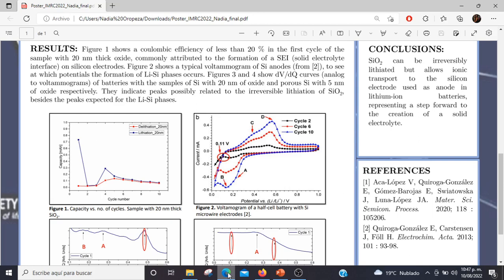As an example, figure 3 shows curves of the first and third cycle of the lithiation period of the silicon electrode for the sample with 20 nanometers of oxide. In cycle 1, there are peaks that disappear in cycle 3. One can be attributed to the SEI formation and the other to the irreversible lithiation of silicon oxide. These peaks are also shown in the 5 nanometer sample. Despite these irreversible reactions, silicon continues to be lithiated, indicating that lithiated silicon oxide allows ion transport.